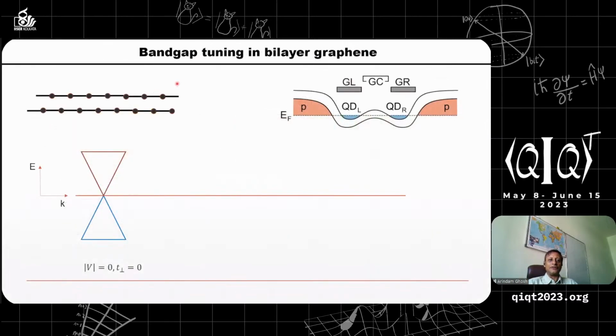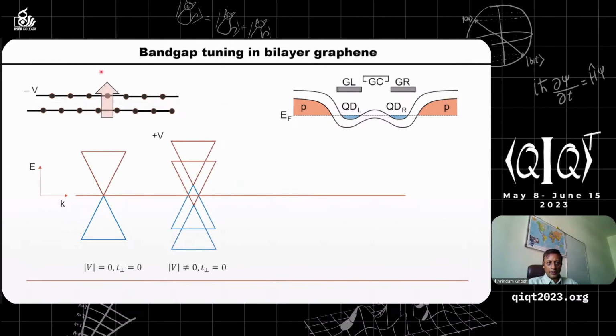What is bilayer graphene? Bilayer graphene essentially is two layers of graphene, which are separated by about 0.3 nanometer, 3 angstroms distance. Now, if you assume that these two layers are independent of each other, then they will have graphene-like electronic bands, like these conical bands I told you about in the beginning. Now, if I apply an electric field perpendicular to the plane of bilayer graphene, these two cones of the two layers start shifting with respect to each other in the energy direction.